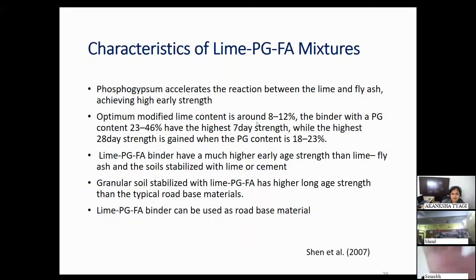Optimum modified lime content is around 8 to 12%. Binder with the phosphogypsum 23 to 46% has the highest 7-day strength for this particular study, while the highest 28-day strength is achieved when the phosphogypsum is 18 to 23%. And granular soil is stabilized with the lime. PGFA has higher long-age strength than typical road-base materials. And therefore, from this study, which is a study based in China, it was seen that the lime, PG, and FA binder can be used as a road-base material.